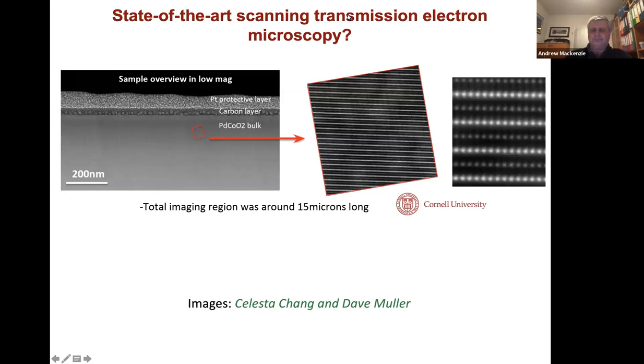And you might think, go to state-of-the-art scanning transmission electron microscopy. And so Celeste Chang and Dave Muller at Cornell collaborated with us to do that. Celeste's got this beautiful graph where you start out at low mag, you're not seeing any defects in the crystal. You increase the magnification, you don't see any point defects. You increase the magnification still further until you're looking at individual atomic columns, and you don't even see any contrast differences atom column to column.